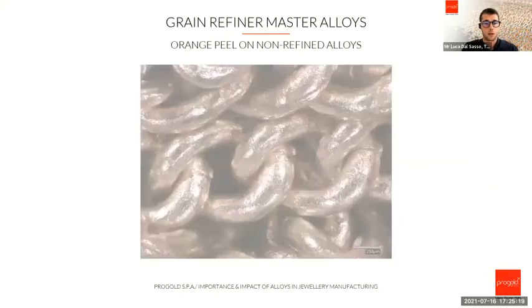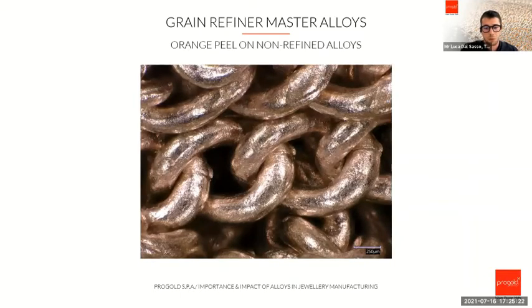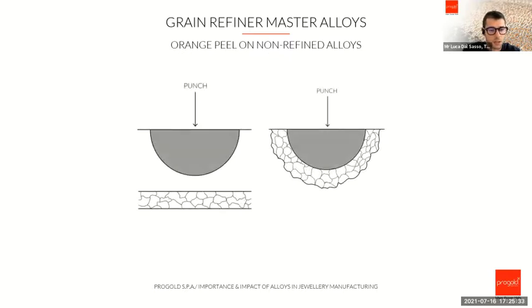The defect I was also mentioning before is the orange peel, and here we can see an example of a chain with a clear orange peel defect on the surface. But let's have a quick look at this image that will explain better how a grain refined alloy helped us to reduce it. As you can see, after the punch on the right, there's a huge difference between the upper side of the grain and the lower one.